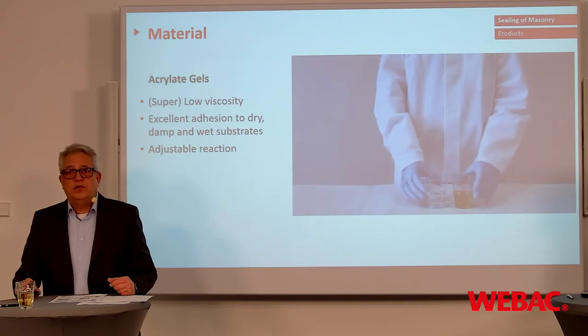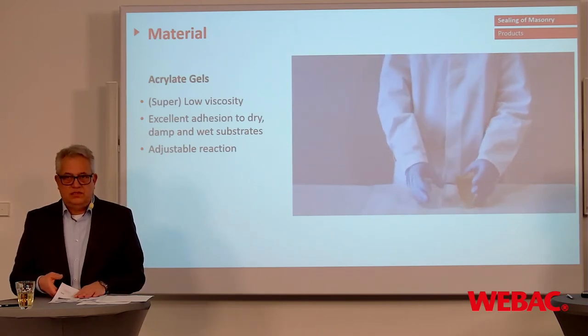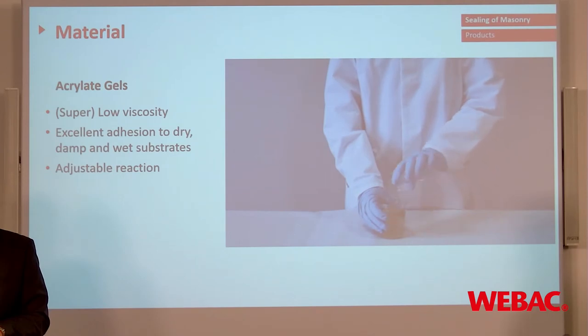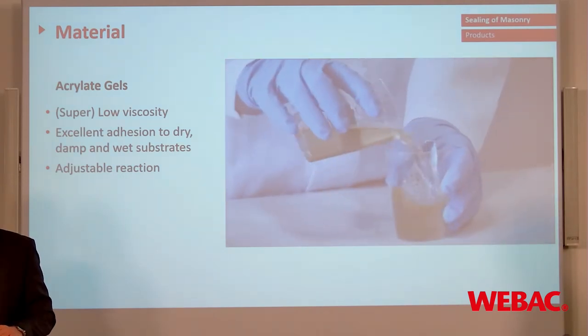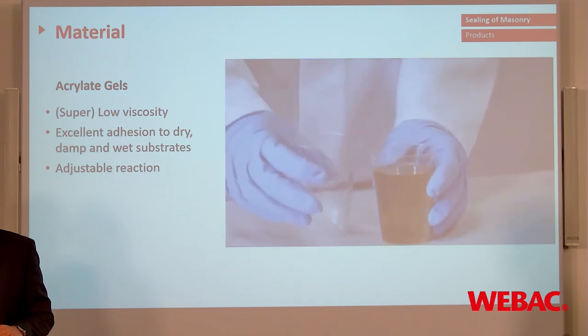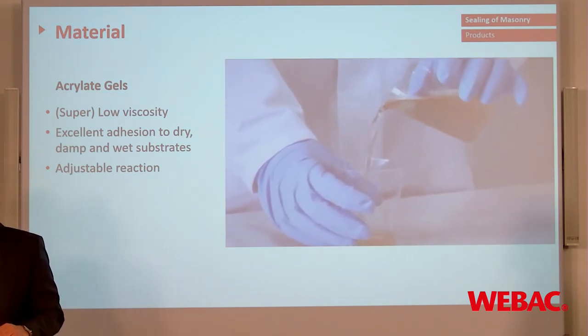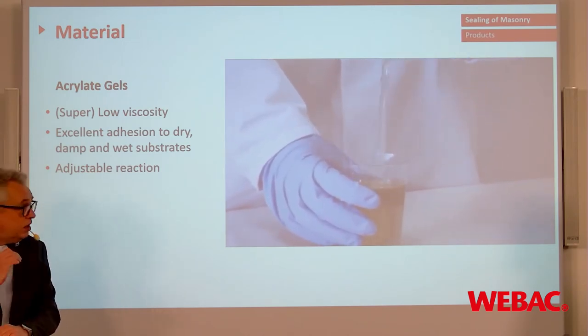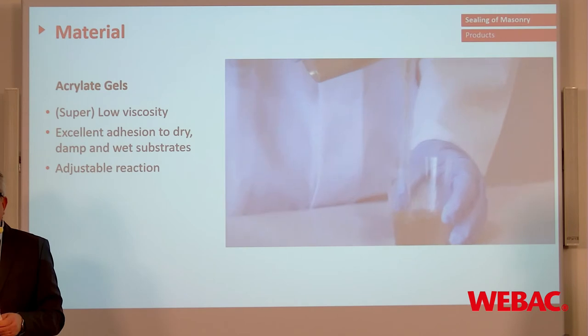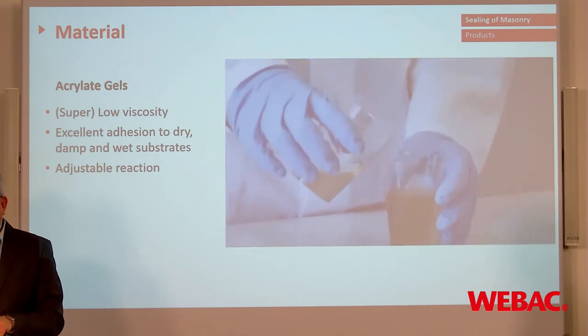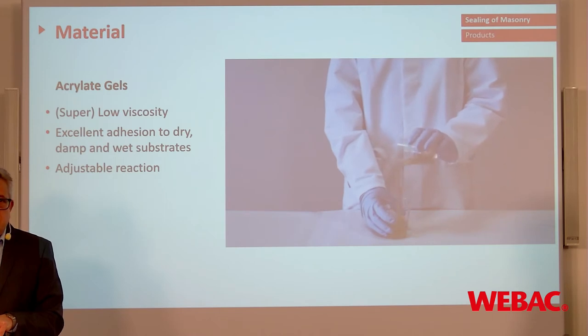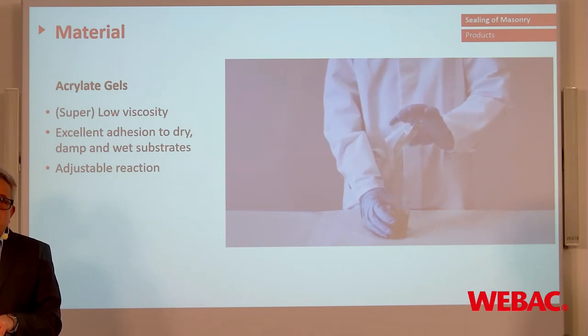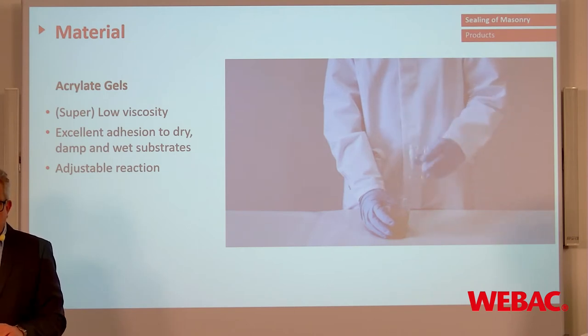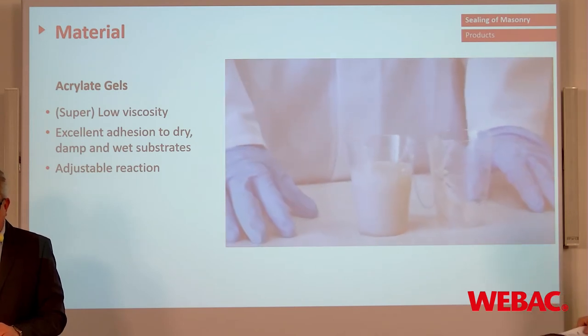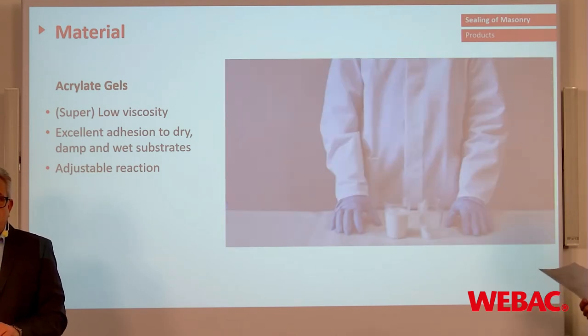Another class of material are the acrylic gels. They are more and more in the focus of the industry because there you have the big advantage that this material has an even lower viscosity than polyurethanes. So we are talking about 5 millipascal seconds. They also have excellent adhesion to dry, damp, and also wet substrates. And they are adjustable in the reaction time.